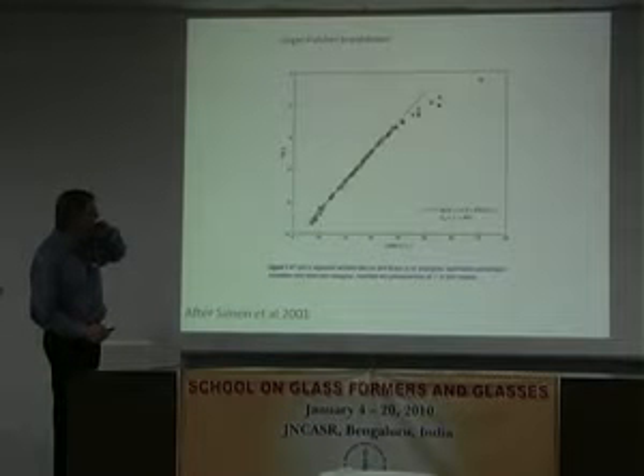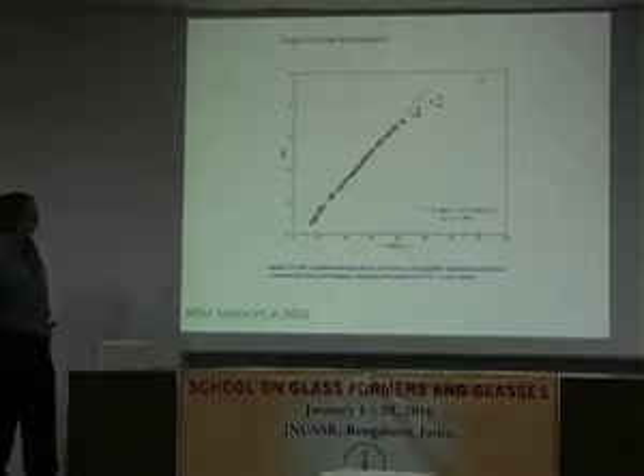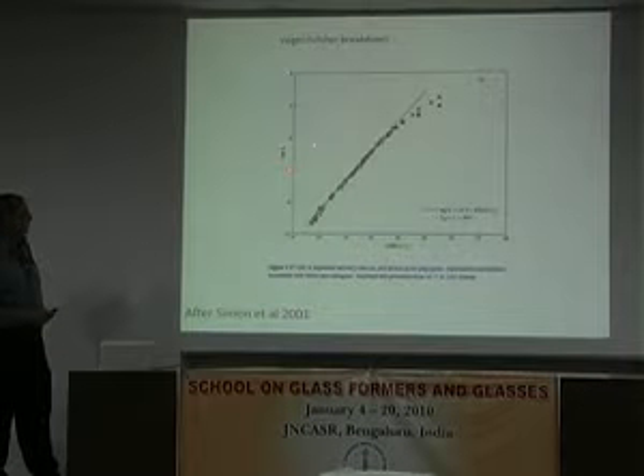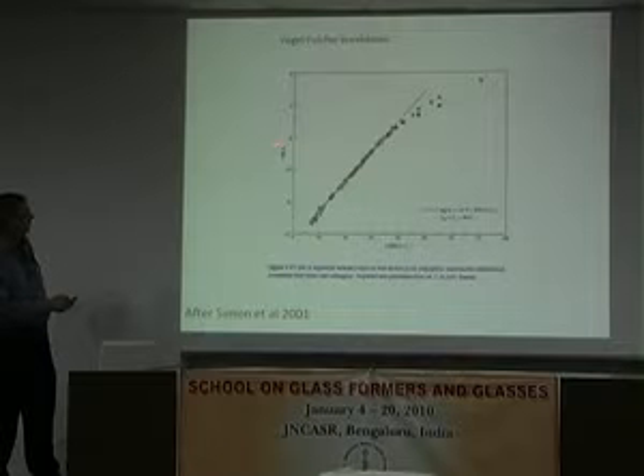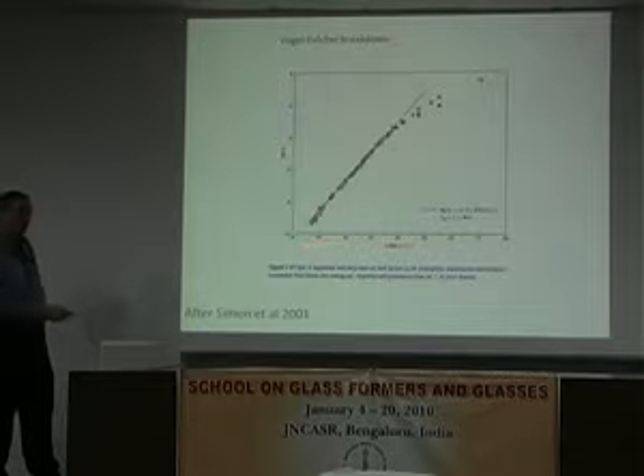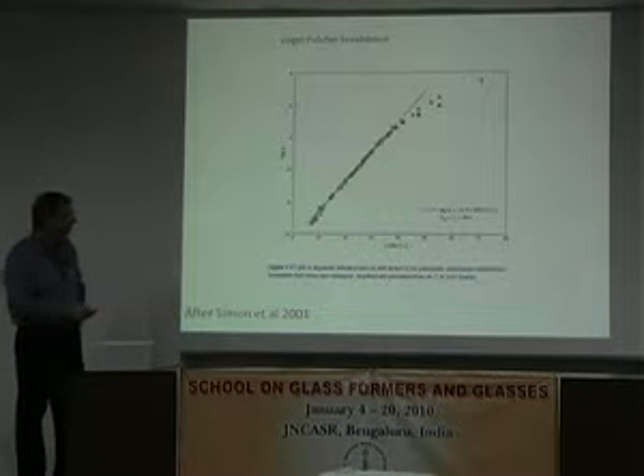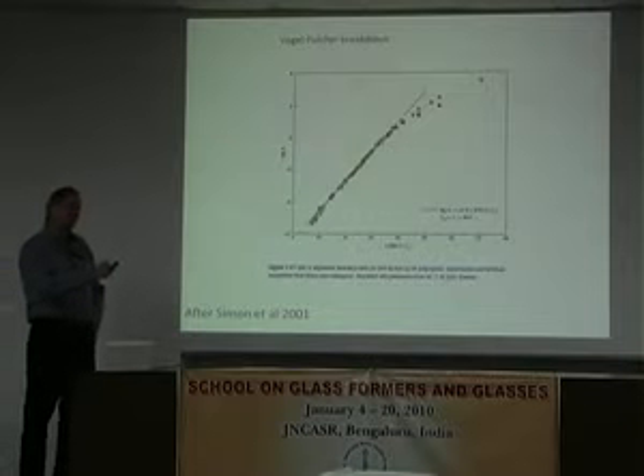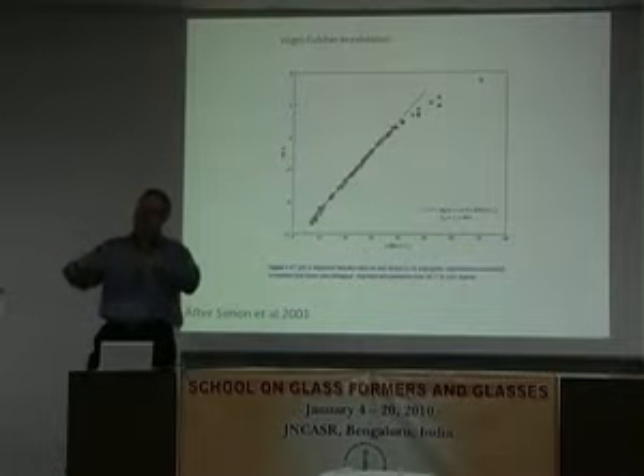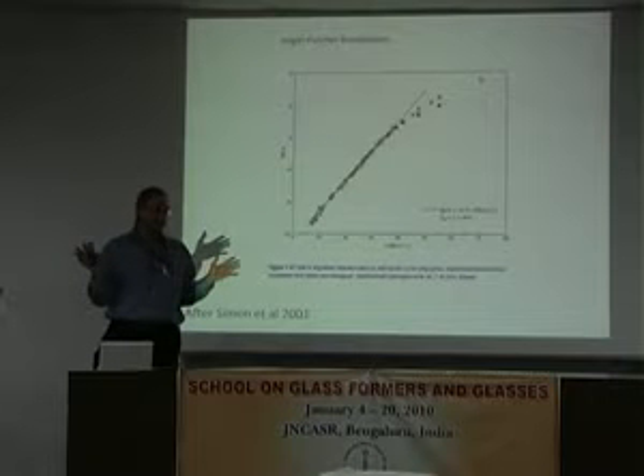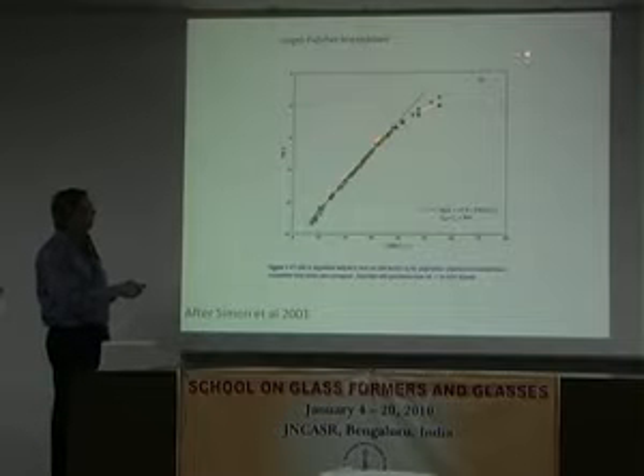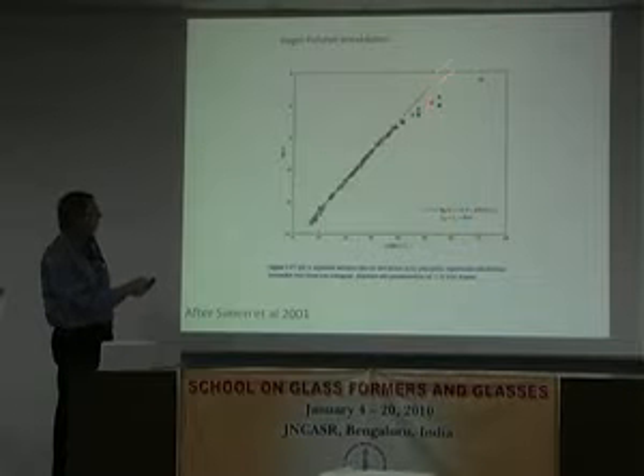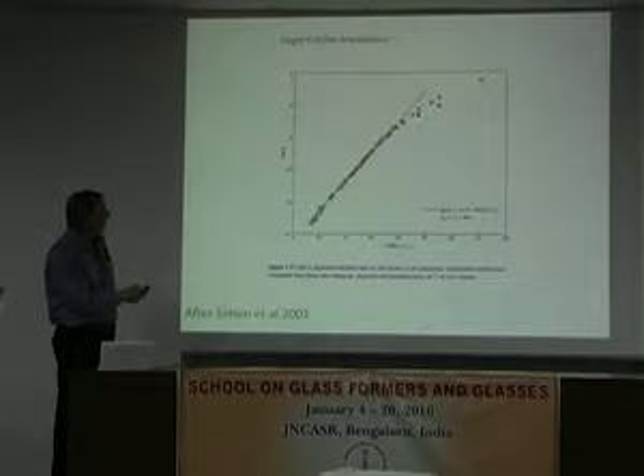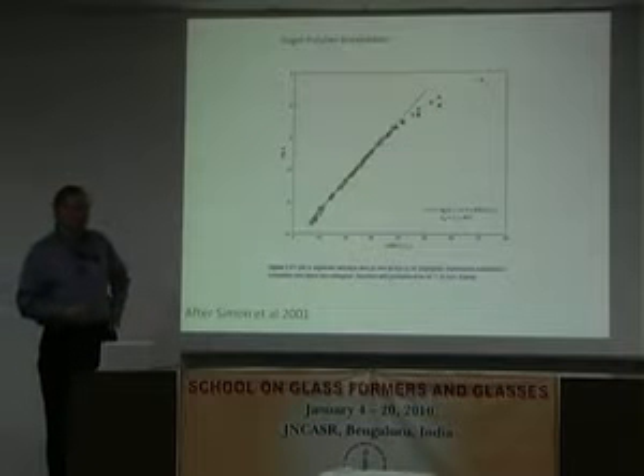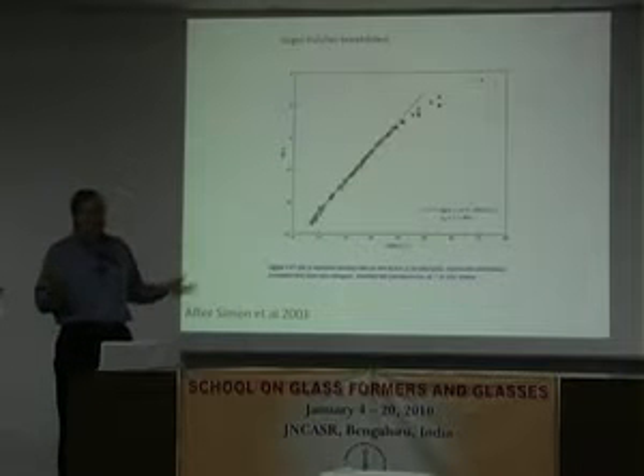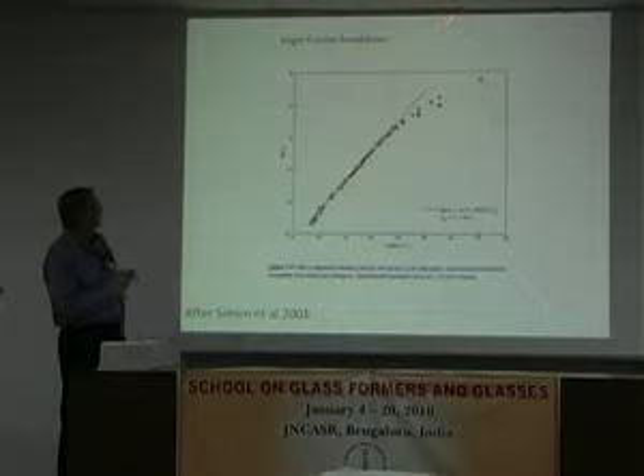And then here's some other data that Cindy Simon and her students did, where they were actually looking at the log of the reduced viscosity or shift time, or reduced time. And now this is a Vogel-Fulcher plot. If it's a Vogel-Fulcher plot, this 1,000 over T minus T infinity, then it should be a straight line forever. And she went back and found some of her own data and also other data from the literature that people hadn't interpreted. And what you find is that there's other evidence, and this is going way below the Vogel-Fulcher line again, too. So in fact there are other examples in the literature of deviations from Vogel-Fulcher. Hence, the interpretation is that at least Vogel-Fulcher breaks down.